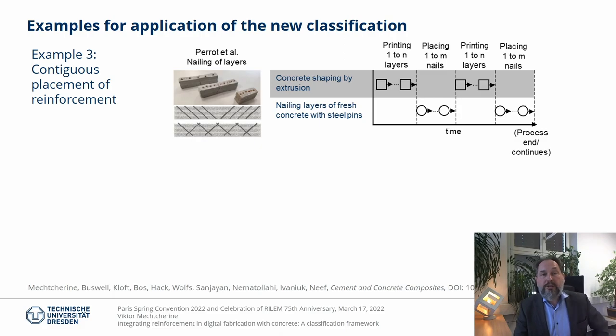The third example illustrates the single-step process in which concrete is shaped additively by extrusion and cross-layer reinforcement is introduced continuously. First, several layers of concrete are deposited one upon the other, followed by piercing layers of fresh concrete with steel pins. After a distinct number of pins is inserted, the concrete printing is resumed to deposit further layers before the procedure is interrupted again to give way to penetrated pins. Such alternation can be repeated numerous times until the printed product — in this case a wall-like demonstrator — is completed.